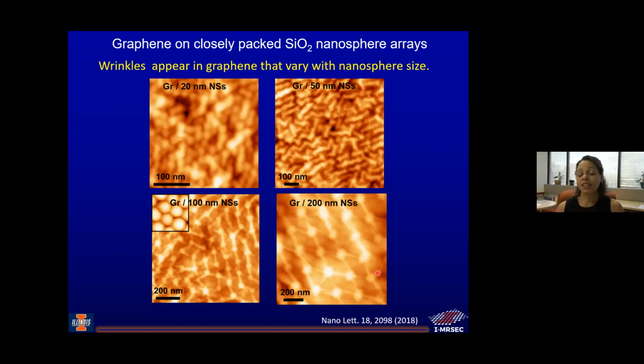Okay, so this is interesting. It tells you that the wrinkle pattern in graphene is modified by the strain, and that different nanosphere patterns give different strain to the graphene itself, right? Because you get different wrinkle patterns, it implies that different size scales give you different strain. So now we're not just looking at strain, but we figured out a way to control the amount of strain in the graphene. So how do we determine how much strain?